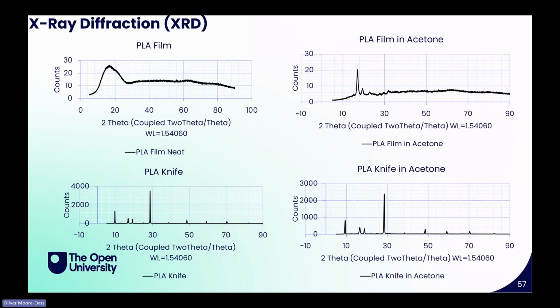To confirm that, we ran another X-ray diffraction. So it's very clear when you see the film how the peak in the crystallinity region has changed and become more prominent. That basically means the amorphous region partially degraded or dissolved, resulting in increased crystallinity detected by the XRD. On the bottom row, you see the knife, and there's not much difference.